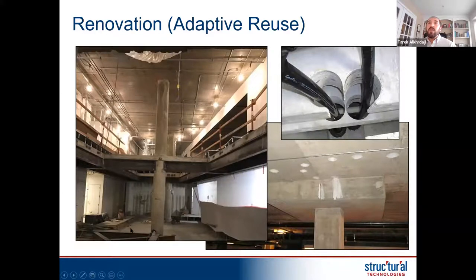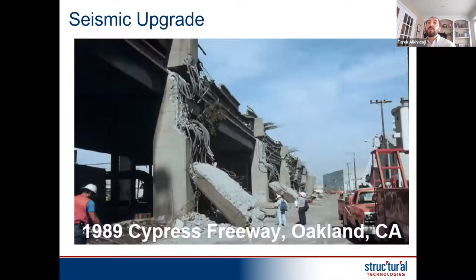The photo to the left, you see the big one, this entire opening was cut into the slab, and this is a post-tension slab. You can see the edge of the slab, you can see these dots, it's basically the anchor location where the PT was anchored before the opening was cut. So some of these changes in the loads and the load path can require additional reinforcements, and that can be done with carbon fiber.